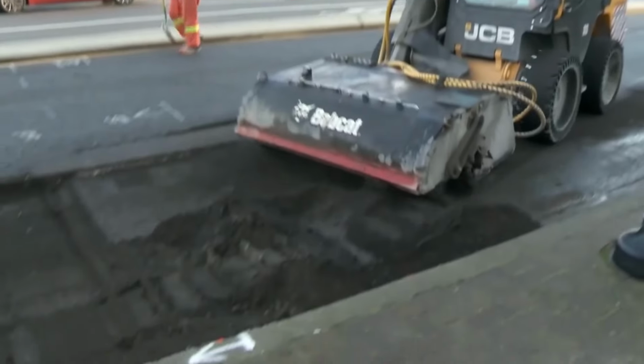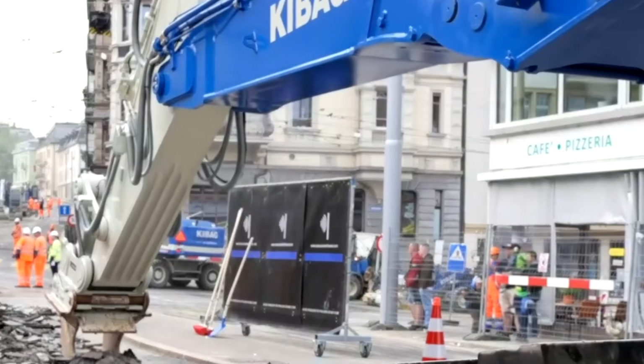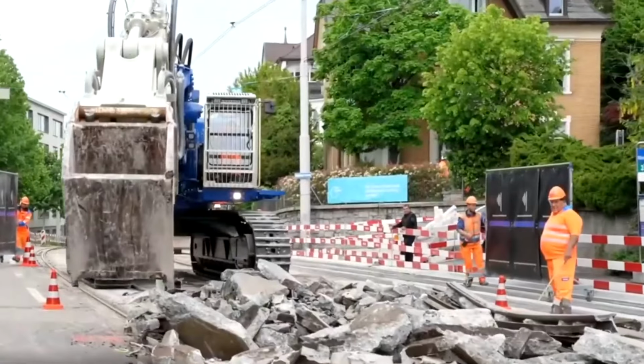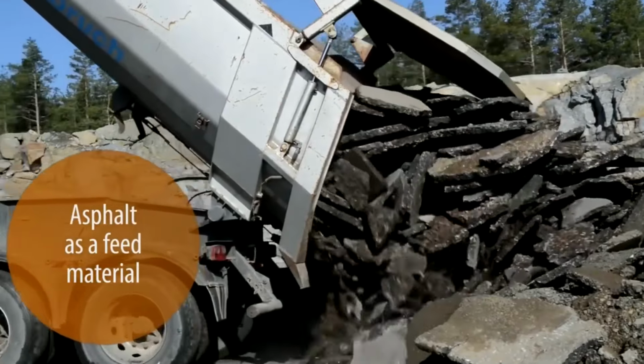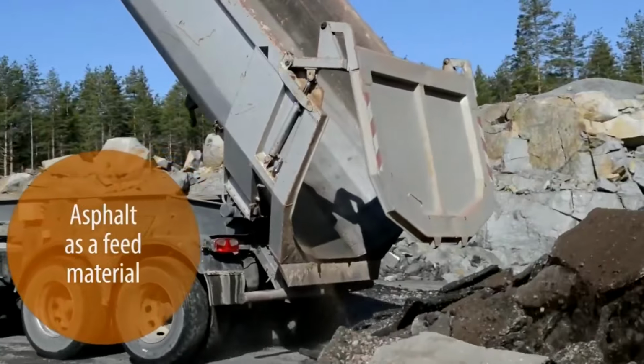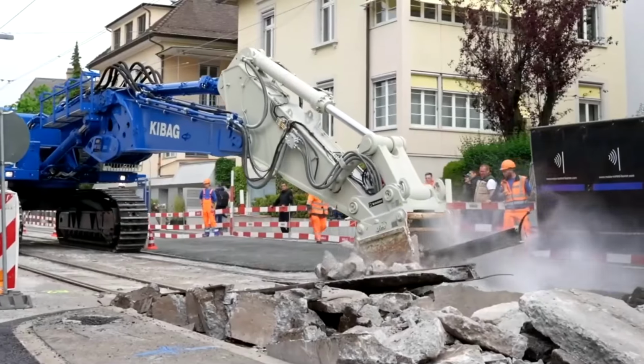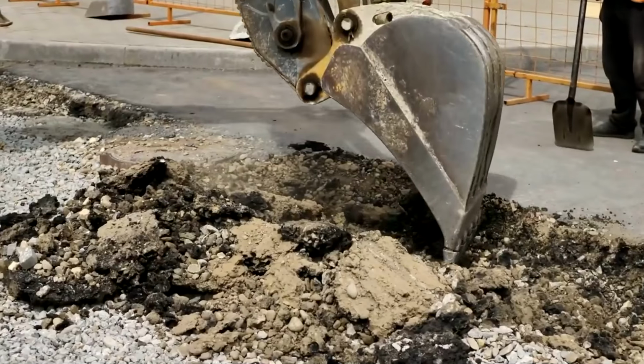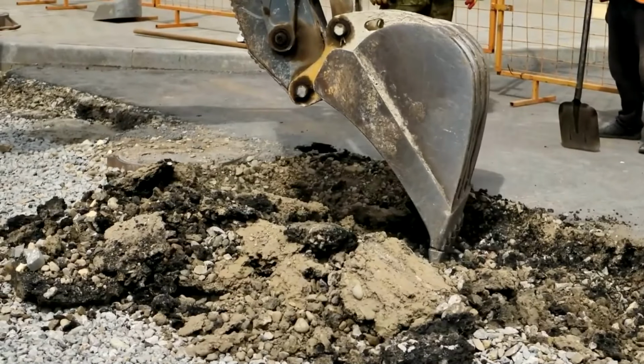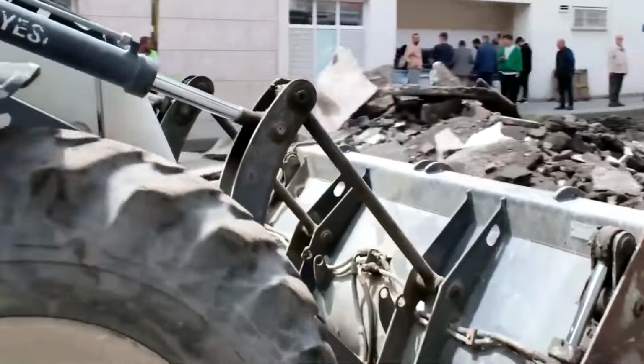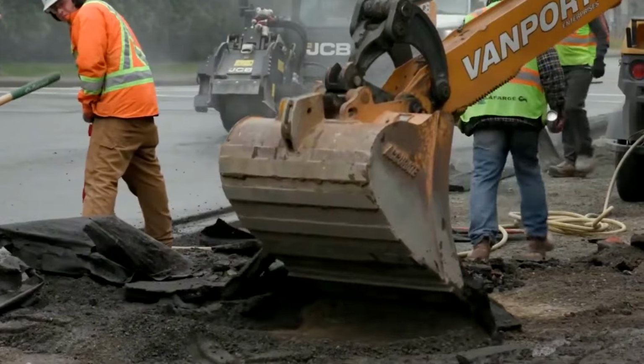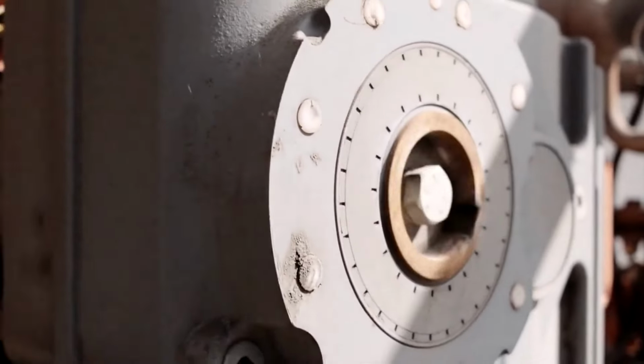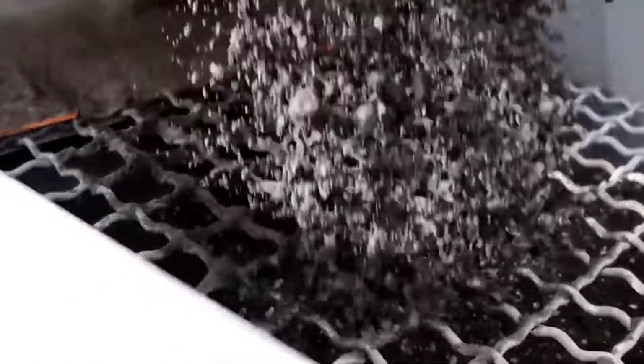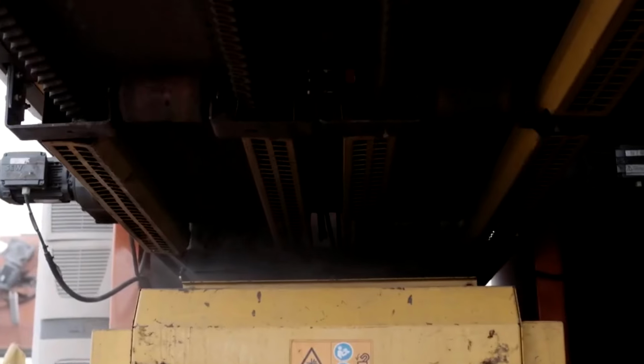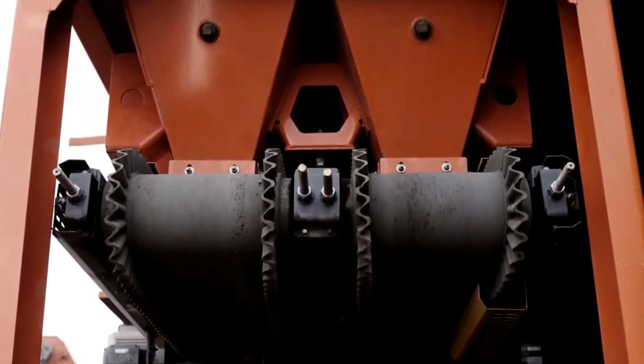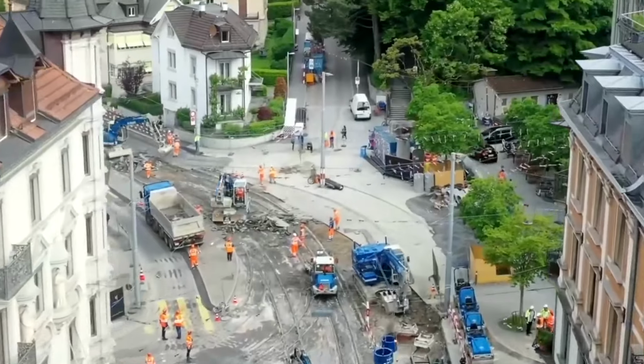After the old pavement is removed and transported from the site, all the material is sent to a recycling plant. Here, every ton of used asphalt begins a process of separation, cleaning, and size standardization, preparing it for the next stage of mixing. Trucks unload the asphalt into a feed hopper, where the material moves along a vibrating feeder that separates debris, soil, scrap metal, and concrete fragments collected during milling. One can notice how large metal pieces are extracted by an electromagnet while the remaining material enters the impact crusher.